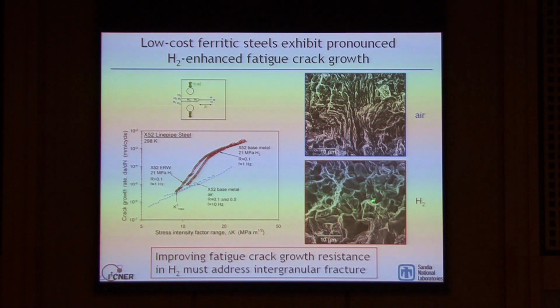As Professor Ritchie was talking about this morning, these cracks in low-strength ferritic steels can actually propagate along grain boundaries, and I'll explain what that means on the next slide. This is a very different fracture mode than what we would see in air. So one emphasis we could develop in this thematic area is, if we're going to improve the fatigue crack growth resistance of these low-cost ferritic steels in hydrogen, we need to understand this intergranular fracture phenomenon.